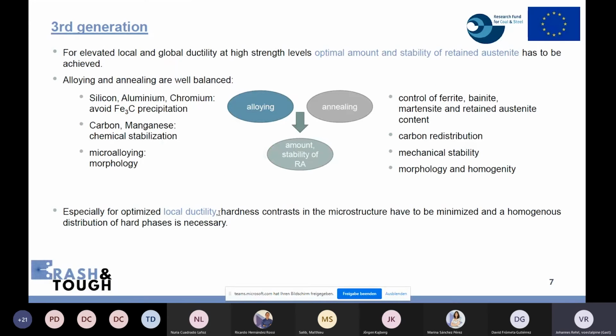Well, to get this elevated local and global ductility for these third generation grades, a particular content of retained austenite and optimal stability of the retained austenite has to be achieved. So we have to say that alloying and annealing are well balanced for these grades. For alloying, for example, we use silicon, aluminum, chromium to avoid the cementite precipitation, so to have the carbon in solid solution to stabilize the retained austenite. Then we have carbon and manganese in the steels for chemical stabilization of the retained austenite.